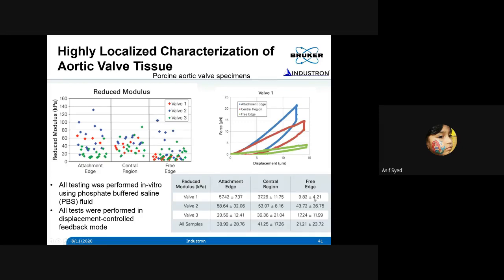As I mentioned, from this load displacement curve, you can calculate the modulus. It is about 57 kPa for the edge region, which is the blue curve. At the central region, it is about 37 kPa, and at the free edge, it is about 10 kPa. So it is how it's supposed to be. That gives you an idea, when you develop this kind of valve, what to expect at various regions and how to tune the property to have the right function. You can use this kind of instrumentation technique to understand that and then tune it. I thought this was a very important contribution to the biomaterial community. Now they have a tool to measure this and fine tune their development.